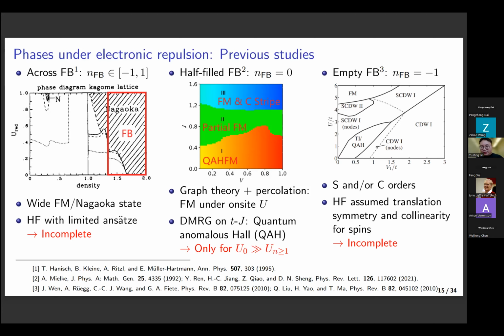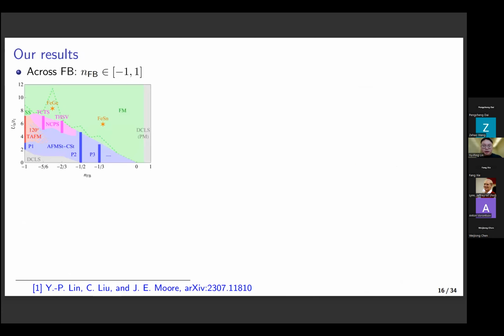So after we found that the previous analysis may be incomplete, we tried to do our own Hartree-Fock analysis. Let me now show you briefly the result. First, we look at the phase diagram across the flatband. And in addition to the ferromagnetism, we find many different phases. For example, we have the stripe orders and also the non-collinear orders like 120-degree spin order and the noncoplanar order.